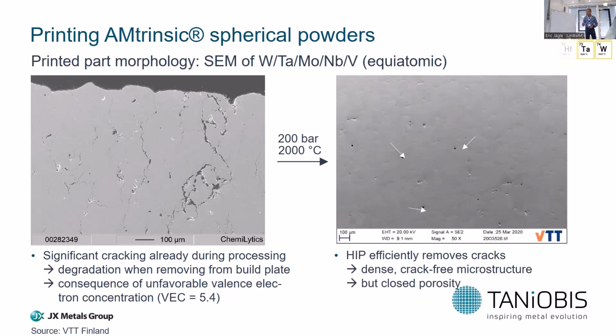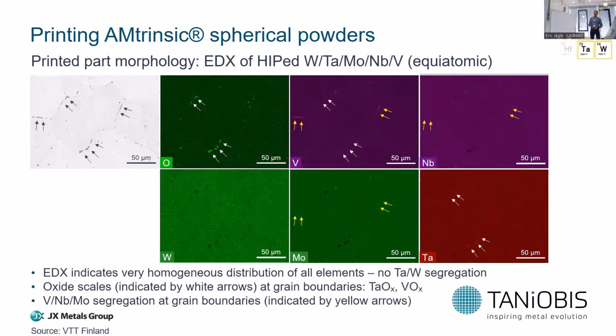If you're looking at the EDX images and electron microscopy images, you see that you have some segregations at the grain boundaries, crystal boundaries. Those appear dark. And if you go into the elemental maps, the EDX images, you can see there are two types of segregation. The first one is composed of oxygen, and if you compare these images, you can see that oxygen appears together with tantalum and vanadium. So we have vanadium and tantalum oxide species at the grain boundaries. And on the other hand, you have segregations which are rich in vanadium, niobium, and molybdenum. Accordingly, we have two types of segregation: oxide segregations containing tantalum oxides and vanadium oxides, and elemental segregations enriched in vanadium, niobium, and molybdenum.